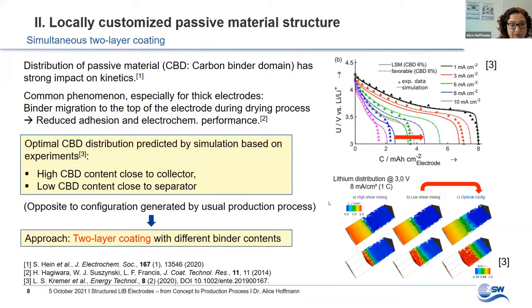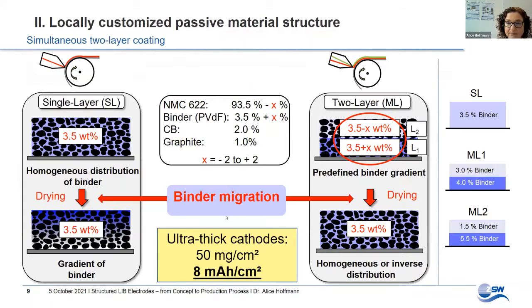However, due to the common phenomenon of binder migration, which occurs during the drying process of electrode fabrication, this optimal arrangement is opposite to the structure that is usually generated in practice. An approach to realize it, nevertheless, is a simultaneous two-layer coating, as I will explain on the following slide. Typically, when the solvent is evaporated, as shown here for the drying process after a usual single-layer coating, it takes along binder to the upper surface. This so-called binder migration is enhanced by high drying rates and leads to an impairment of adhesion and electrochemical performance.